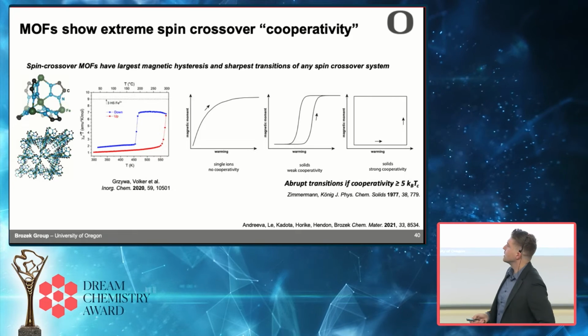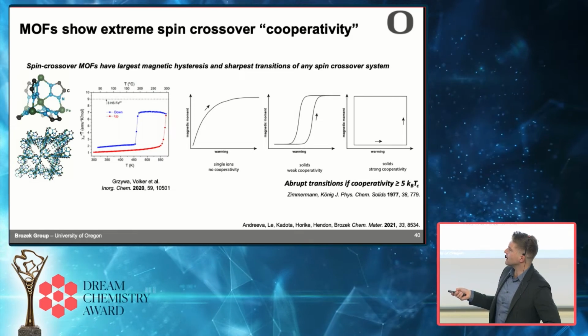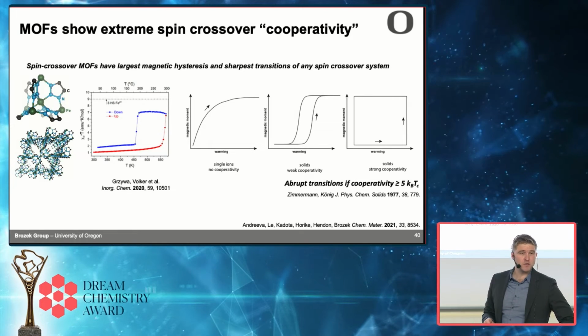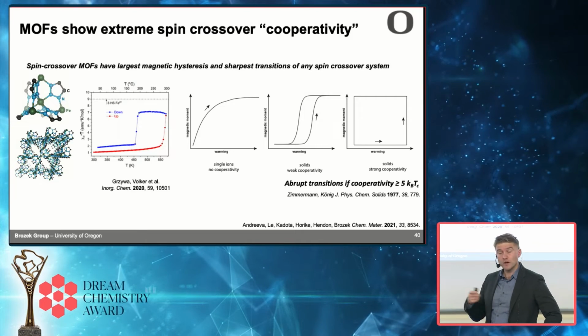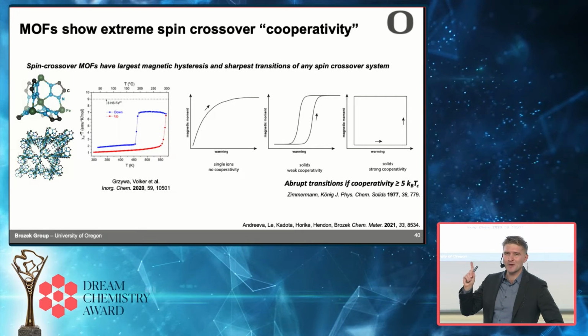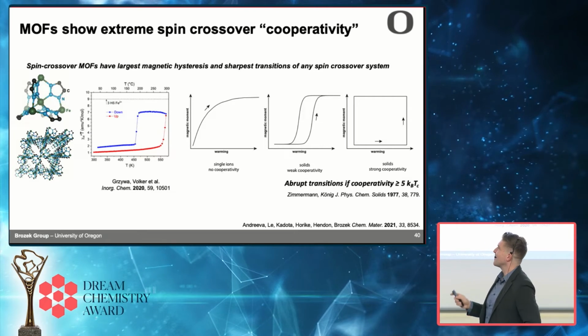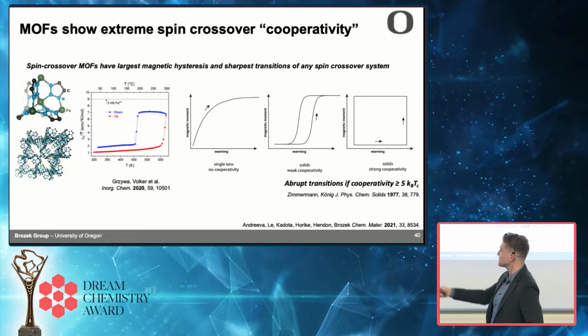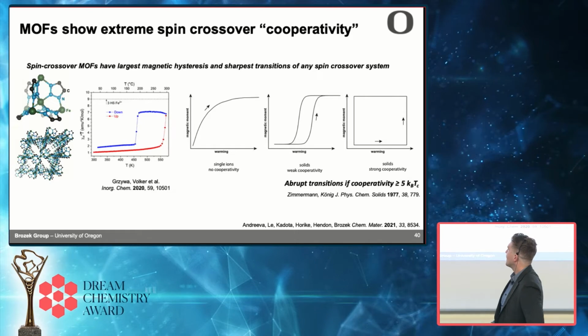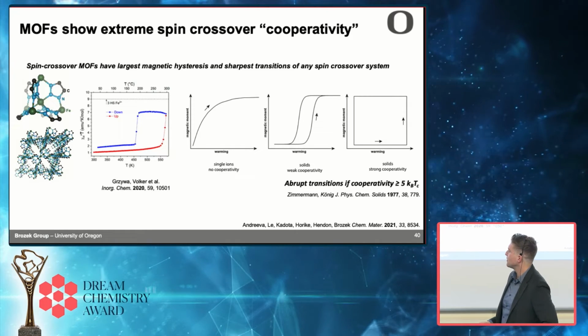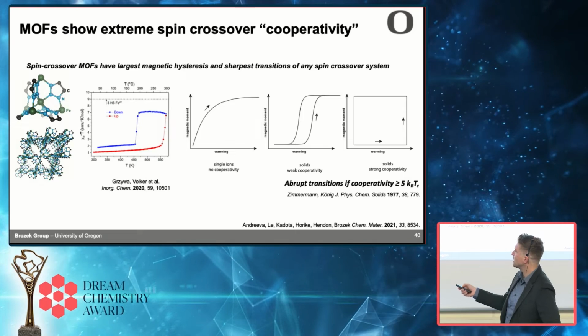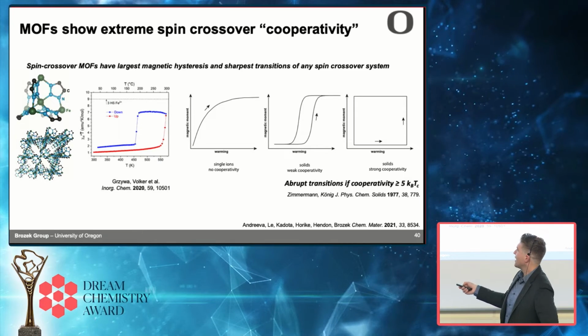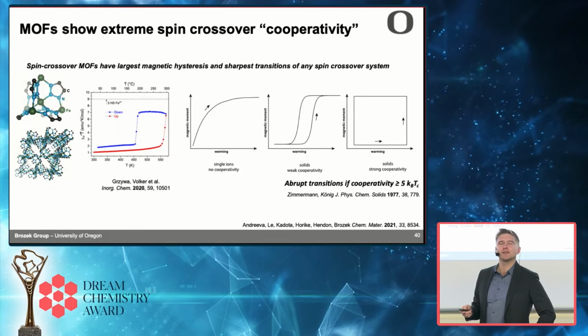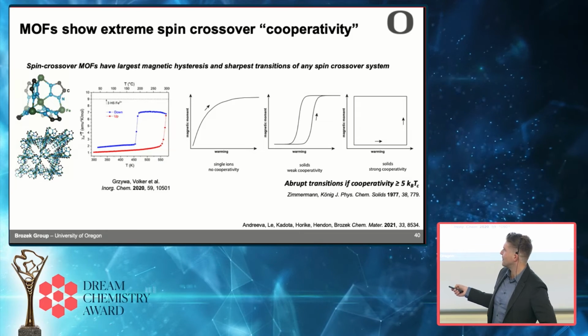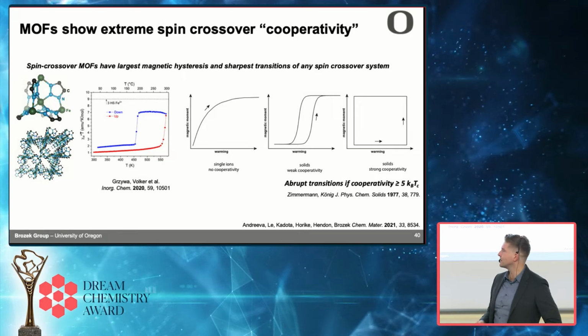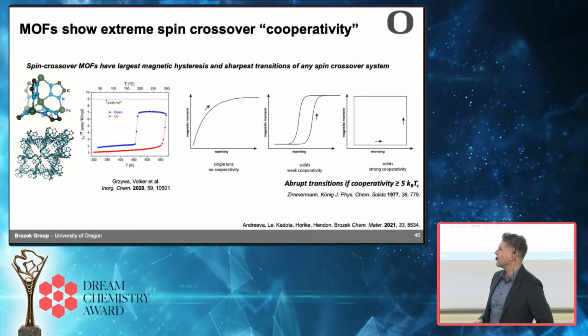But the data here for iron triazolate actually looks much more like this perfect box-shaped behavior that people had predicted in the 70s. So it turns out iron triazolate has the widest hysteresis window of any spin crossover material, or one of the widest, because I know there's going to be someone out there who says, no, there's this one paper. But this is among the widest hysteresis windows and the sharpest transitions. And so in the 70s, people predicted that you would get this sort of behavior if the cooperativity in your material was 5 times the thermal energy around the material. So 5 times kT.